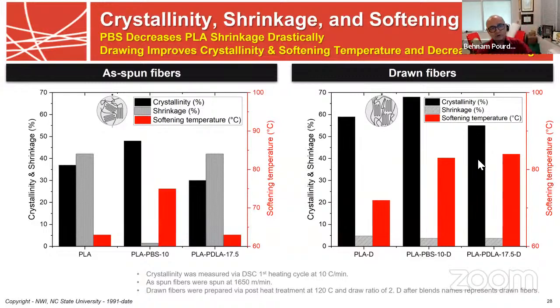But I also want to note that sometimes we actually like smaller crystals. So for example, for filtration, we like smaller crystals and lots of them, because, for example, we trap charge inside the defects within the structure. So for the drawn fibers, you actually have two options. You can use either PBS or PDLA. And really for partially drawn fibers, you have no choice. You have to use PBS. And it impacts the performance very, very significantly.